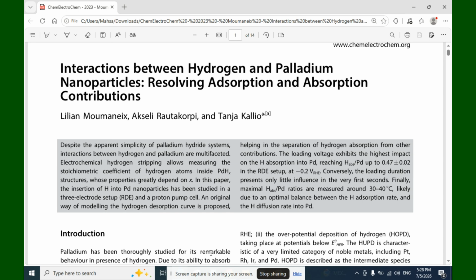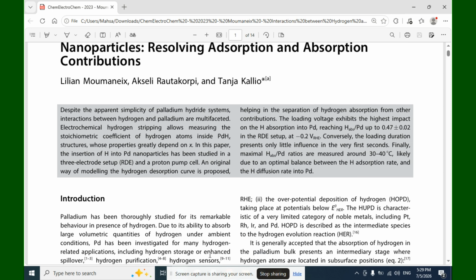contributions. The loading voltage exhibits the highest impact on the hydrogen absorption into palladium, reaching hydrogen absorption per palladium up to 0.47 ± 0.02 in the RDE setup at -0.2 V vs. RHE. Conversely, the loading duration presents only little influence in the very first seconds. Finally, maximal hydrogen absorption per palladium ratios are measured around 30 up to 40 degrees centigrade, likely due to an optimal balance between the hydrogen absorption rate and hydrogen diffusion rate into palladium.